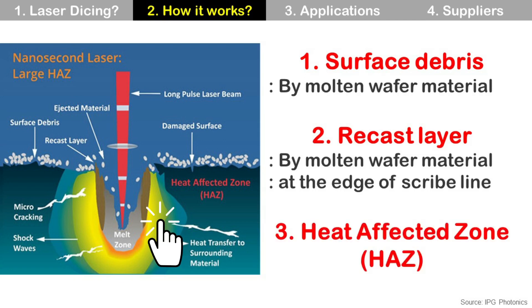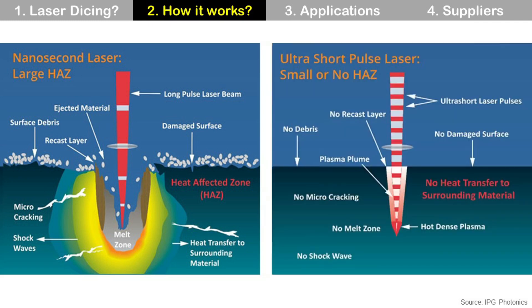The third one is the damage by laser heat. To solve these issues, machine suppliers use laser with shorter duration. People used nanosecond laser before, then moved to picosecond laser.